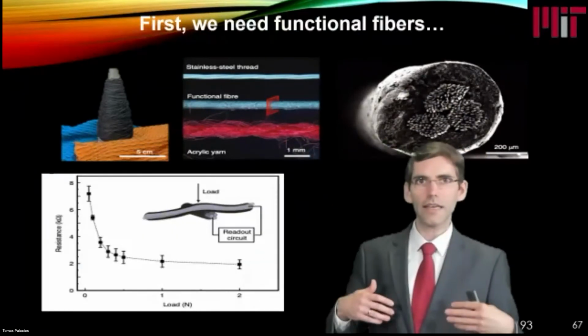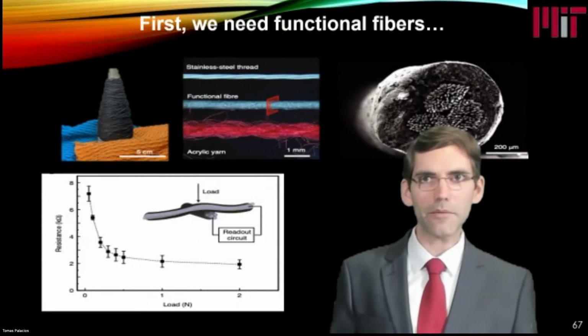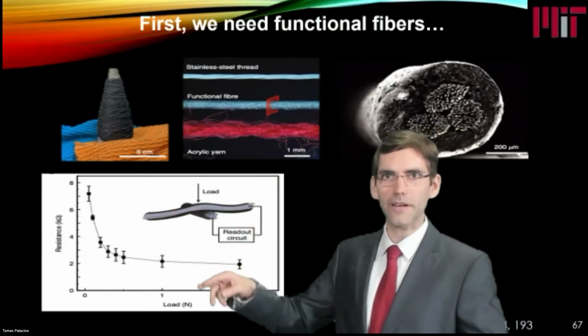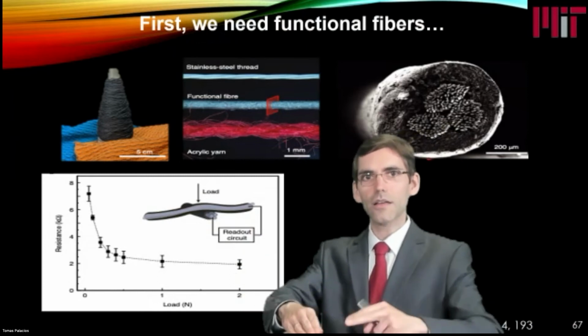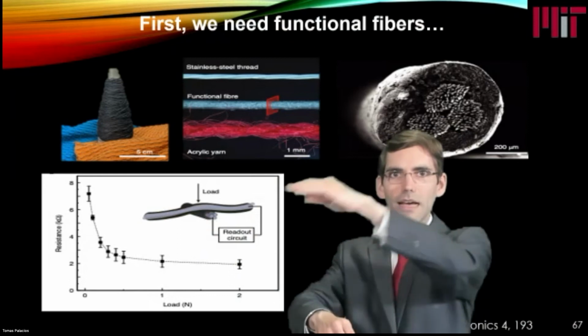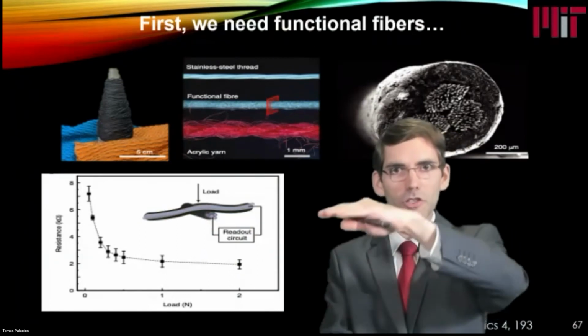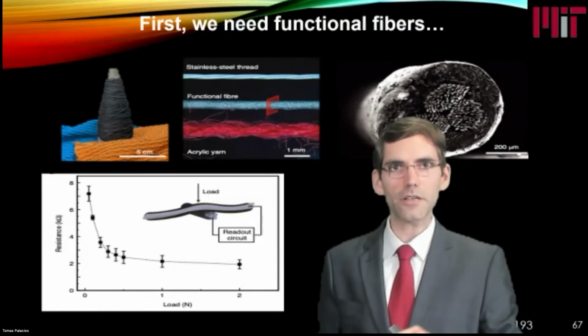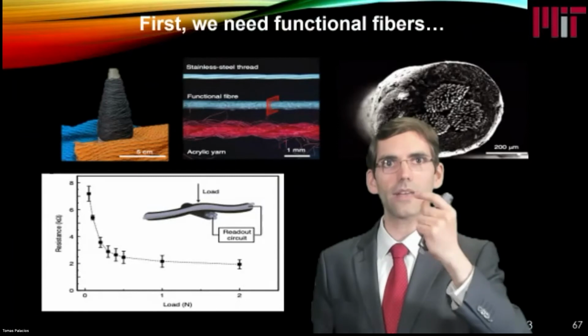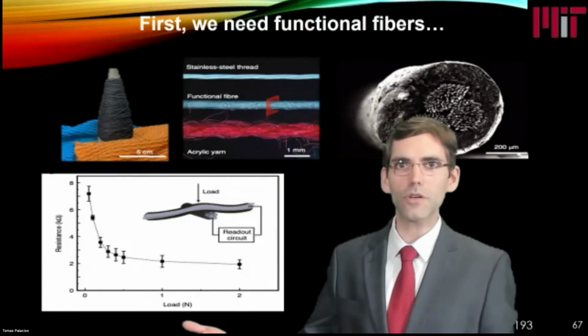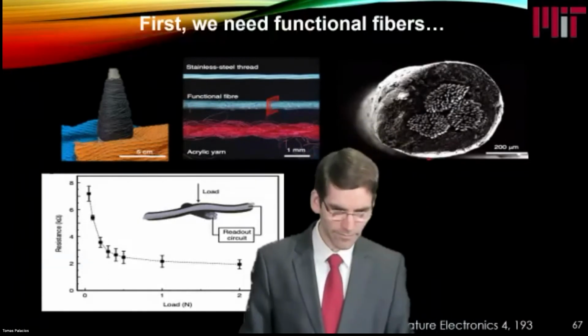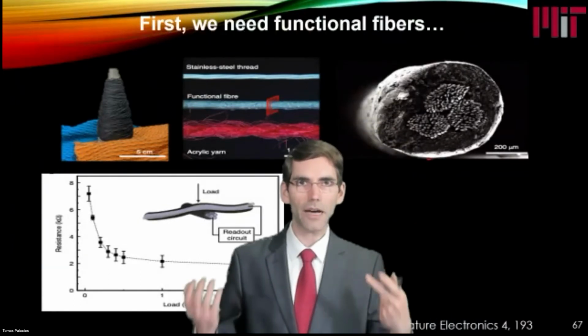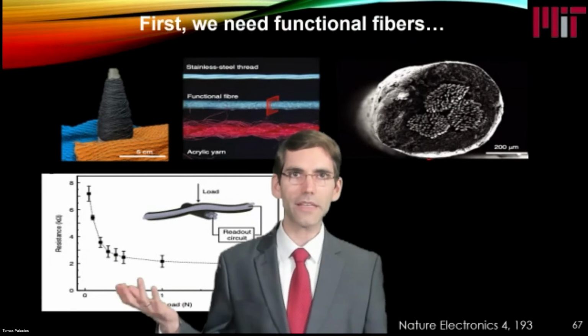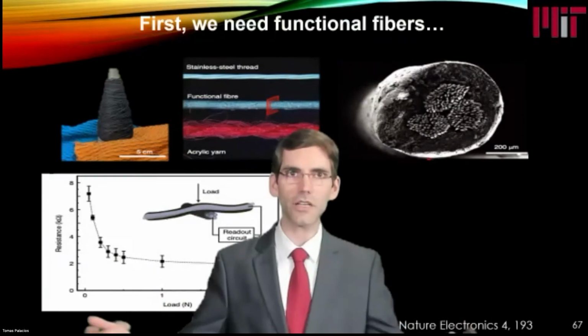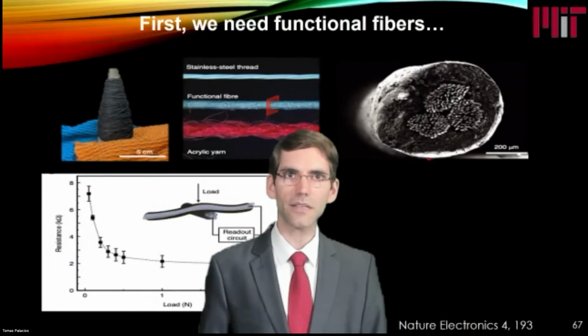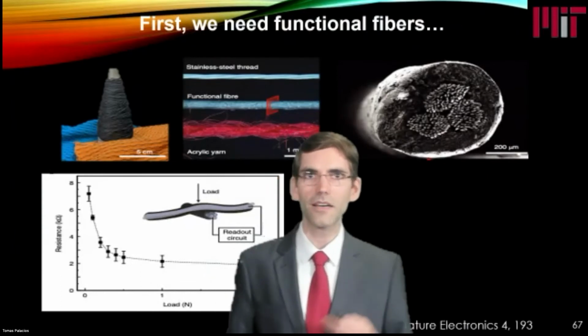And then we built a pressure sensor out of these fibers by just crossing two of these fibers. And the idea is that you have the metal fiber here coated with a graphitic material, and on top a second fiber. As you apply pressure, you are changing the distance between the two fibers, and you are changing the resistance through the graphitic material in between. And in that way, you can measure the force that you are applying. A very simple sensor. But the power of this is scalability. We have these fibers. Now we start building electronic circuits. And the way we build these electronic circuits is very different from conventional electronics. We just start knitting.